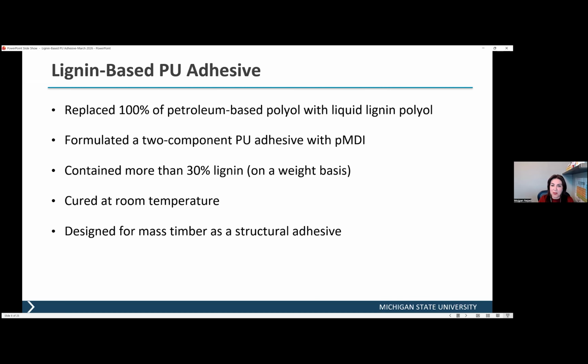As I mentioned, some polyurethane adhesives are one component, some are two components. At this point, we are focusing on two component adhesives. One of them is liquid lignin polyol, and the other is polymeric isocyanate, which is one of the safest aromatic isocyanates that we could use compared to other types of isocyanate. The formulation has more than 30% lignin on a weight basis, and it was designed to be cured at room temperature, similar to commercial adhesives, and is designed for mass timber applications as a structural adhesive.